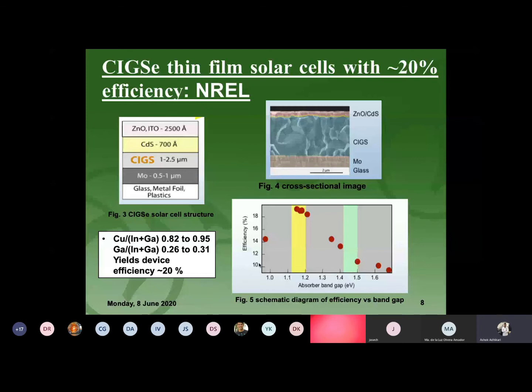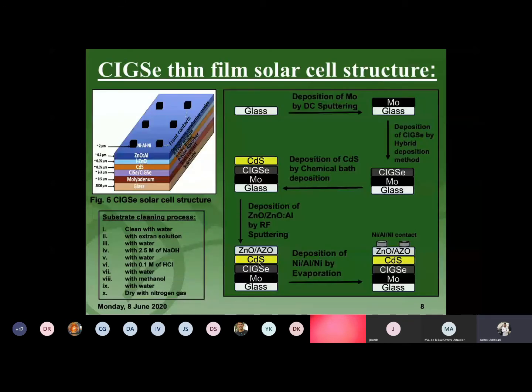Figure 6 is the solar cell structure we are planning to develop in our lab. First of all, the glass is cleaned through water, deionized water, and then Extran solution, subsequently with sodium hydroxide and hydrochloric acid, methanol, and finally dried with nitrogen gas.